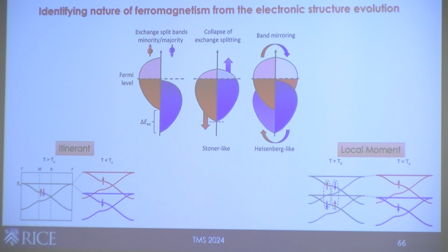In the other limit, if you have a Heisenberg-like local moment picture, then the local moments themselves will persist well above the ordering temperature, which means that locally you will still have the difference between the spin majority and spin minority states, but they lose the long-range coherence. What that means is that on average you will have regions that are spin up and regions that are spin down. So what you will see going across the ordering temperature is that the exchange splitting will still remain, but you just lose the spin polarization associated with each band. So this is a very simple way, from an ARPES perspective, to learn how local or how itinerant the magnetic order is in a given system. You just ramp the temperature across the ordering temperature and see how much of this gap closes.